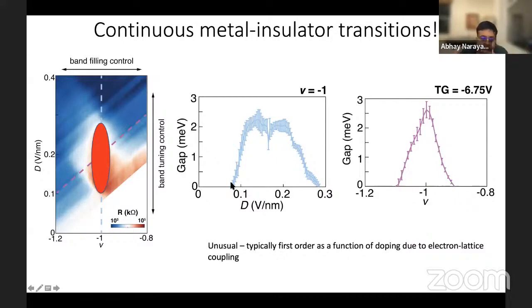And this is somewhat unusual in these kinds of systems. Quite often in, say, complex oxides, when this kind of metal to insulator transition happens, there's also strong coupling to lattice degrees of freedom, and this makes the transition first order. So here it looks like at least the system might have a second order phase transition. And in that case, one might imagine, is there any possibility that there would be a quantum critical transition at this boundary? And so in order to probe that, what we do is we look at transport carefully when we are near these metal to insulator transitions. If you tune density, you have 2 metal to insulator transitions on either side of this half filling point. And if you tune electric field at half filling, once again, you have 2 metal to insulator transitions.